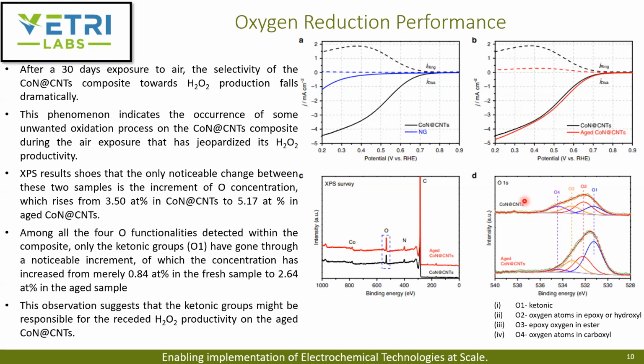So this suggests that the presence of more ketonic groups is responsible for this decreased peroxide productivity on their aged samples.